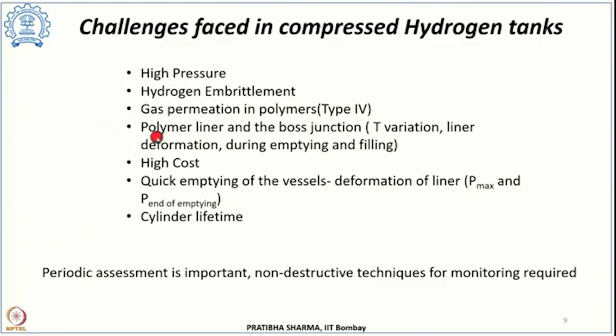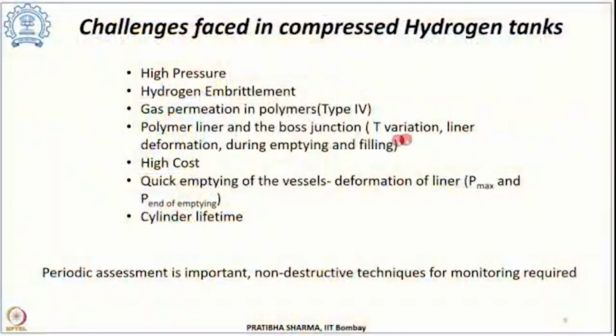Then another important point is the place where the polymer liner is integrated with the boss. So that junction, the polymer liner and the boss junction. Now this is a very important point, and we can get leakage at this point if there is a temperature variation. For example, when the emptying of the cylinder takes place or when the filling up of the tank takes place, there will be a temperature variation. This we have already seen, the compression and expansion thermodynamics of hydrogen. Subjected to that temperature variation, there could be changes at this interface. There can be even liner deformations when such changes occur during emptying and filling of the tank.